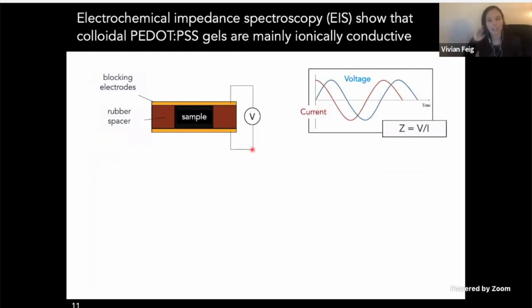To get a little bit more insight into what's going on, we can do electrochemical impedance spectroscopy, where now instead of applying a constant voltage, we apply this AC voltage. And then the impedance, which is the ratio of voltage to current, gives us information not just from the magnitude of the current response, but the phase shift as well.